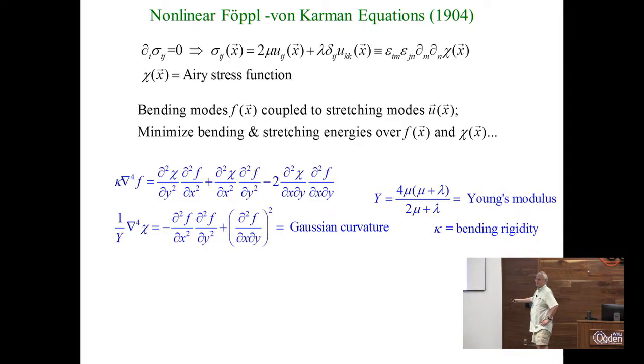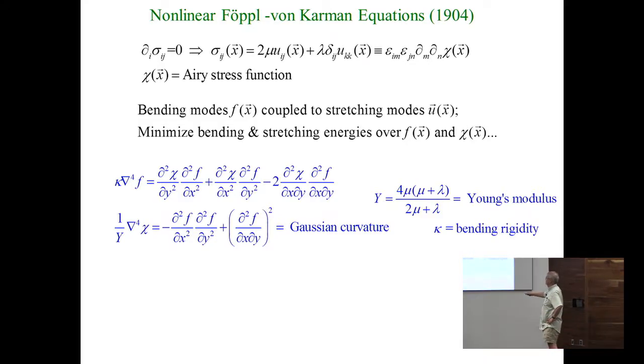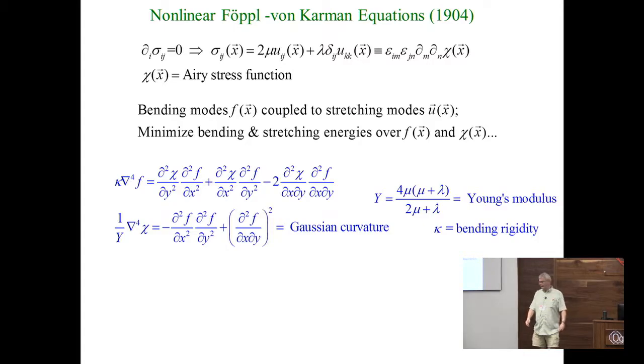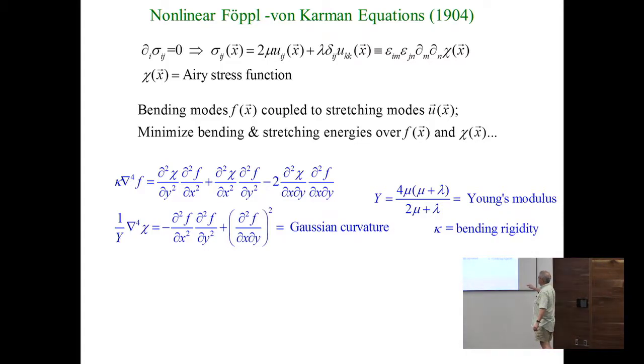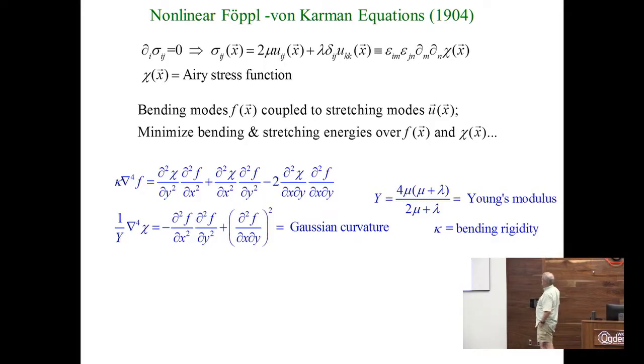This is a baby version of general relativity. In fact, down here you can see that the source in the Laplacian, biharmonic Laplacian squared sense for the Airy stress function that determines the stresses and strains, it ends up being this combination of derivatives of F, which is nothing more than the Gaussian curvature. The Gaussian curvature of this embedded surface in 3 dimensions is a source term over here, and then this is a bilinear nonlinearity over here that balances the bending forces on the right-hand side, and the only combination of elastic constants that matters in this Föppl-von Kármán formulation is the Young's modulus, which is made out of the shear modulus, which is mu, and the bulk modulus, mu plus lambda.